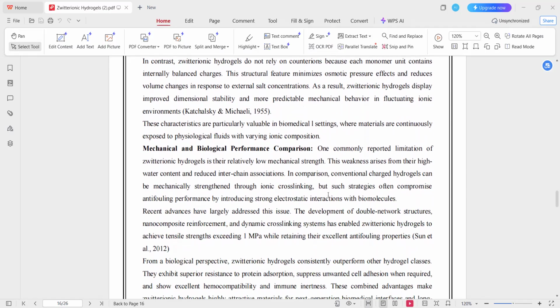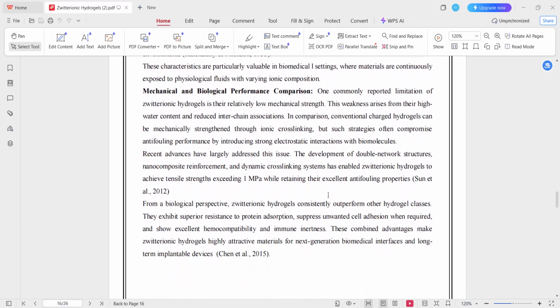Mechanical and biological performance comparison. One limitation of Zwitterionic hydrogel has historically been relatively low mechanical strength due to high water content and reduced interchain associations. Conventional ionic hydrogels can be mechanically strengthened by adding ionic crosslinks, but this often compromises antifouling behavior because the surface becomes more attractive to proteins and cells. Recent reinforcement strategies such as double network formation, nanocomposite incorporation, and dynamic cross-linking have largely addressed this issue. Zwitterionic hydrogels can now achieve tensile strength exceeding 1 megapascal while retaining their ultra-low fouling properties.